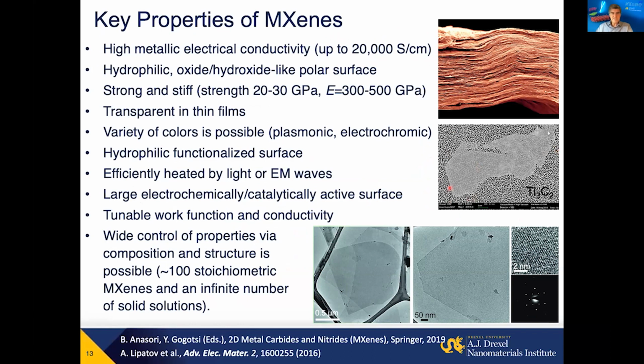Here you can see a single flake, about 20 micron long, a single layer flake of Ti3C2. And actually it's possible to keep such large flakes in solution processing. You will never get MoS2 of that size through solution processing, or oxide of any kind, here because of the very high mechanical strength and modulus of these materials. And they are transparent in thin films, very good for transparent conductors.